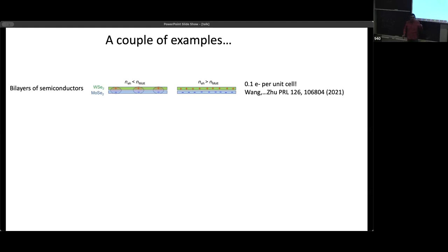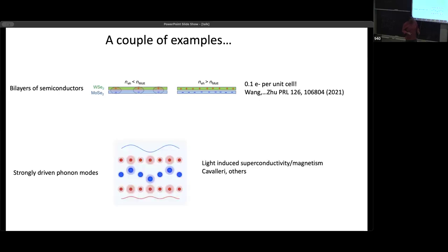Now, if I shine a small amount of light at this sample, I create a small number of excitons. But it is possible to shine so much light at this sample that you create so many electrons and holes that you can have approximately 0.1 electrons per unit cell and 0.1 holes per unit cell when you're shining a laser at this thing. And that is an insane number, right? That's what we normally associate with doping of a crystal. If you do solid state physics and you think about doping, 10% doping is a huge amount of doping. And so simply by shining light at this sample, you can create a 10% doped crystal. And I said, wow, wouldn't it be wonderful if we had some methods to study this kind of photo-doped crystal, where you can dope it by these large amounts?